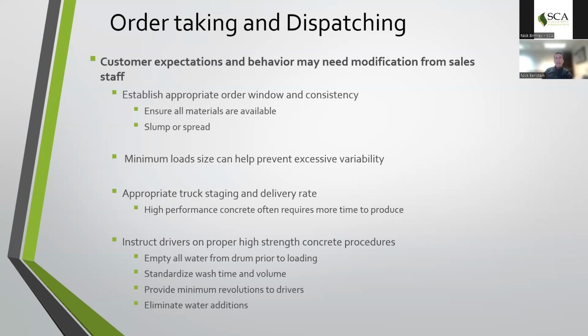And then on more of a local level at an individual plant, working with drivers to ensure that they understand that this is a different type of product, making sure there's no wash water in the drum prior to loading, making sure we standardize wash time and volume. We often do this on a mix by mix basis, as even within high performance concrete, some of the lower strengths might require much less mixing to get to a consistent performance, where some of the higher strength concretes really can have extreme mixing times.